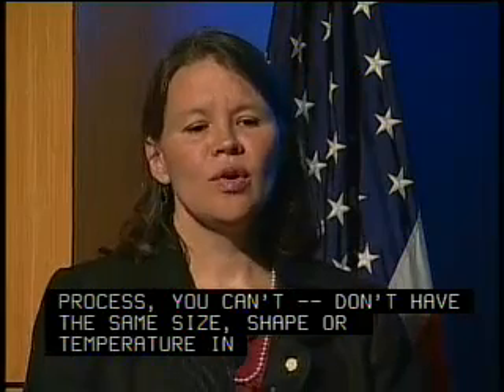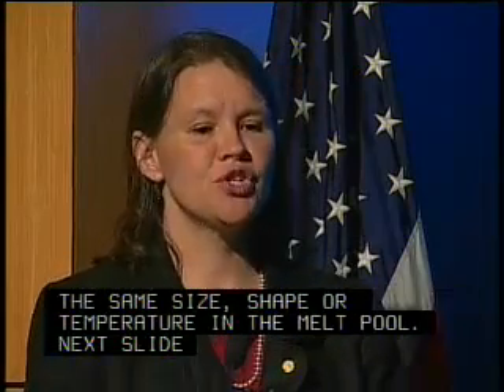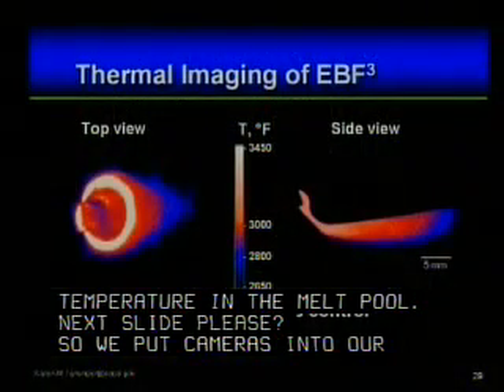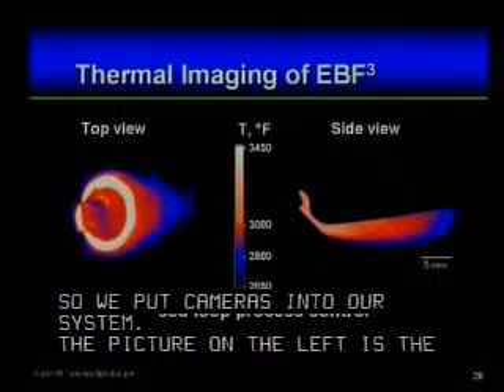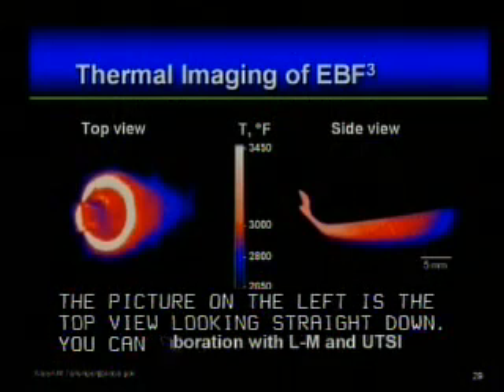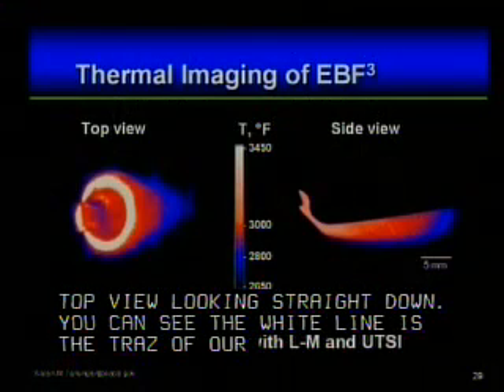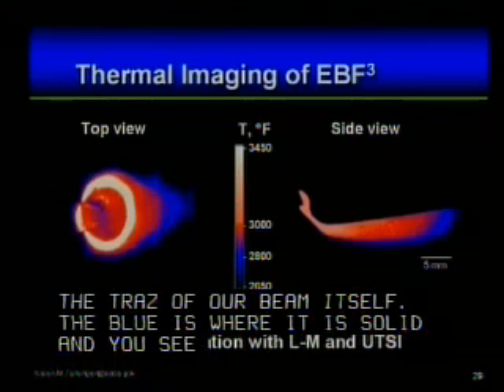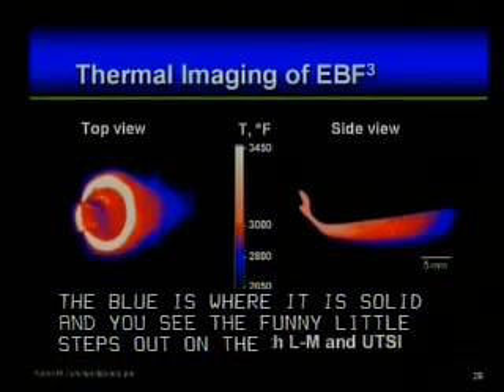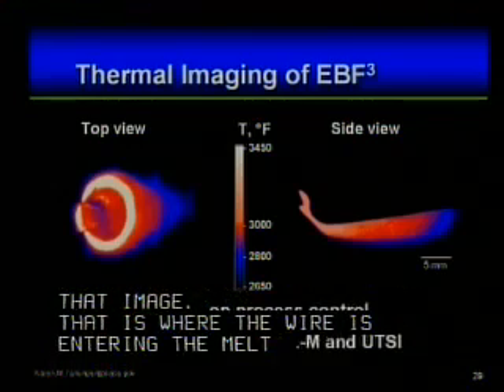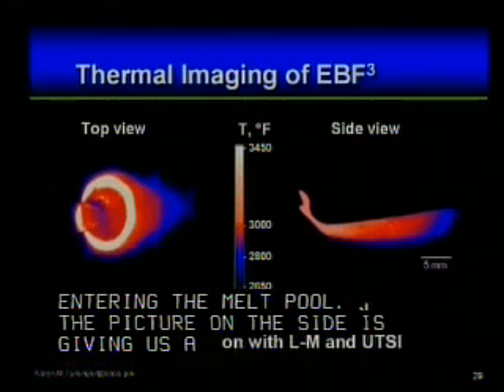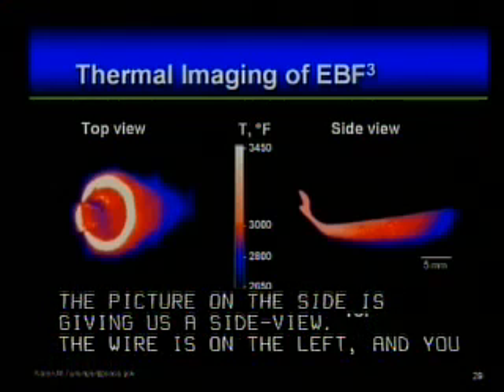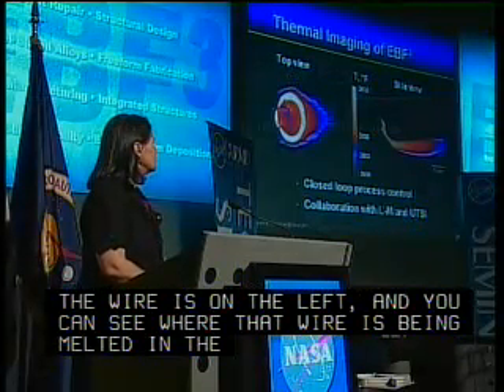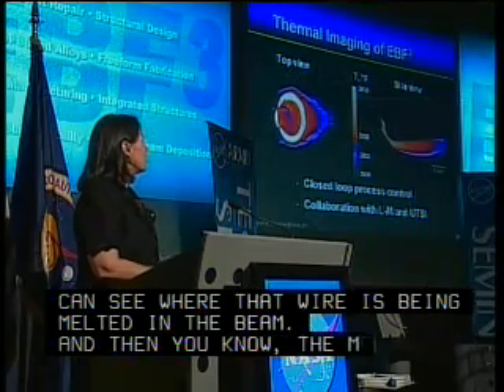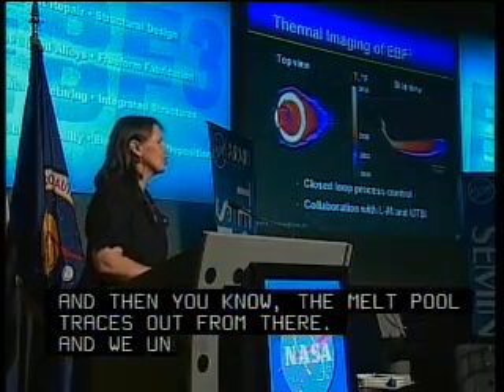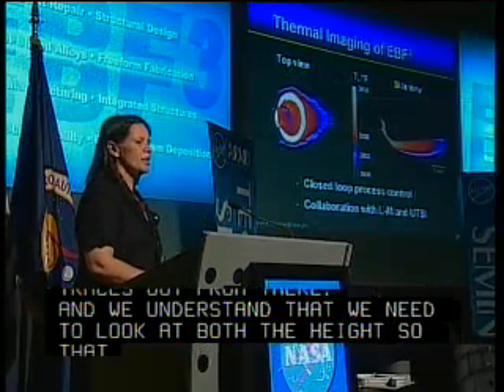Next slide, please. So we've put thermal imaging cameras into our system. The picture on the left is the top view looking straight down. The white line is the trace of our beam itself. The orange is where the metal is molten, and the blue is where it's solid. And you see the funny little step out on the far left of that image. That's where the wire is entering the melt pool. The picture on the side is giving us a side view. Again, the wire is on the left, and you can see where that wire is being melted in the beam, and then the melt pool traces out from there. We understand that we need to look at both the height, so that we build the part that we have programmed to build, and the top view, so that we can control the temperature. Next slide, please.